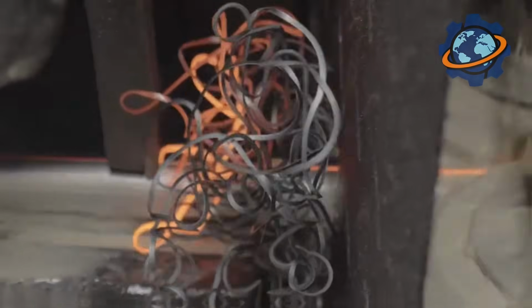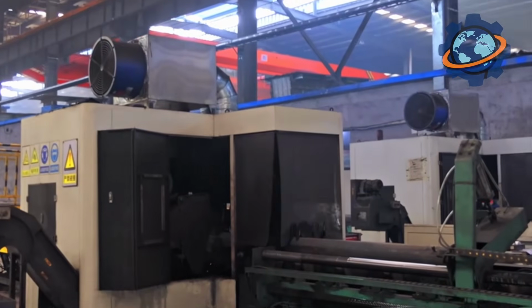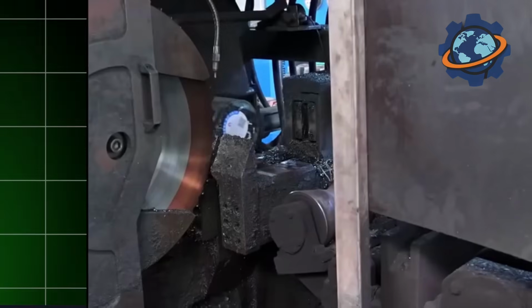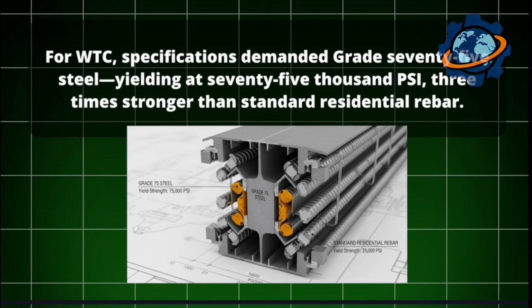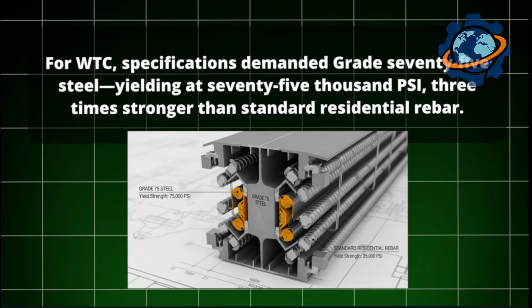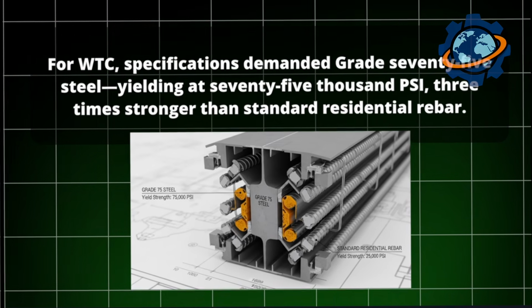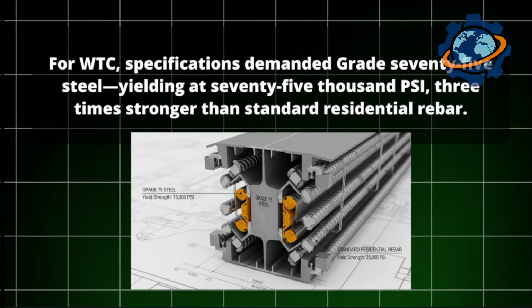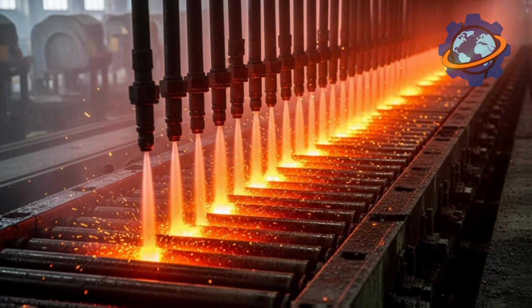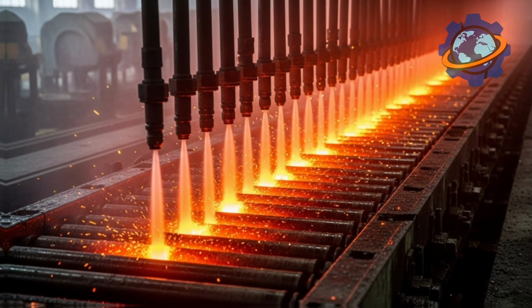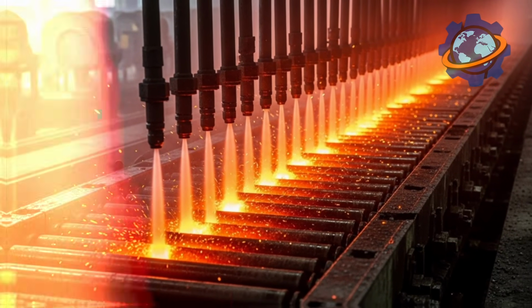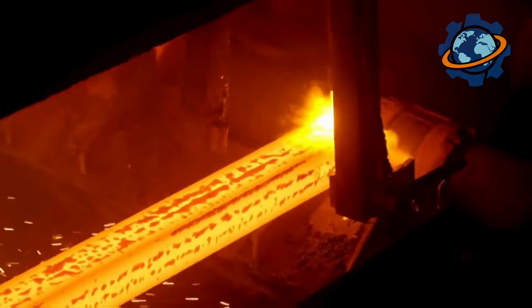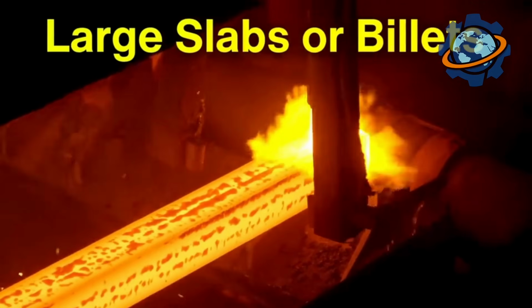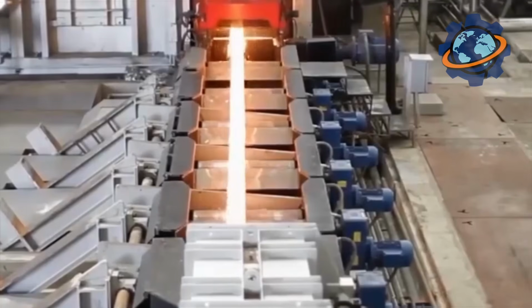The rib pattern follows precise standards: height, spacing, angle, all controlled to thousandths of inch. For WTC, specifications demanded grade 75 steel, yielding at 75,000 psi, 3 times stronger than standard residential rebar. After rolling, the rebar, still 800 degrees, enters cooling bed where water jets control cooling rate. Fast cooling creates hard but brittle steel. Slow cooling produces soft but weak steel.